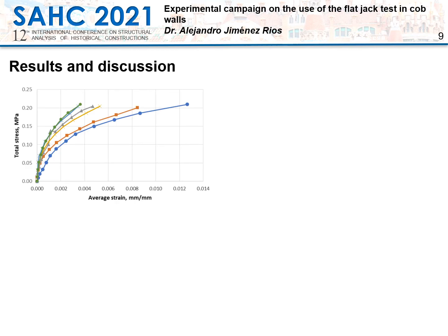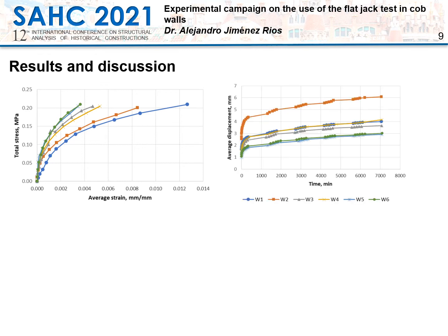As can be seen in the figure, all wallets presented a nonlinear stress-strain relationship during the first consolidation load cycle. The cause of the nonlinearity was not the load level, as it never exceeded a maximum value of 85 kilonewtons, which induced a compressive stress of only 0.21 megapascals in an idealized cross-section of 0.4 square meters. This value represented only 30% of the compressive strength obtained from the cob cylinders.